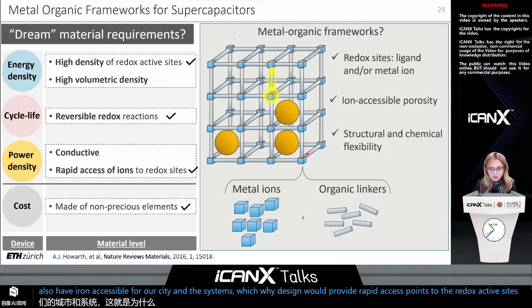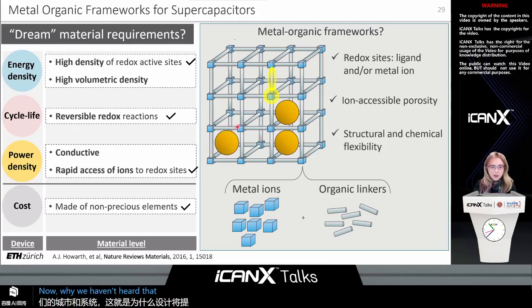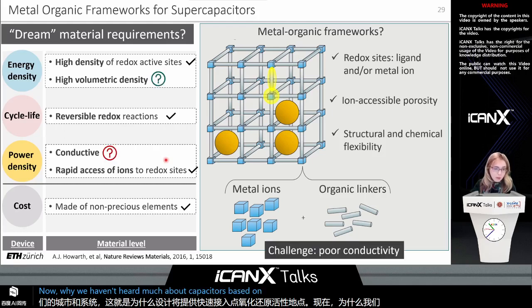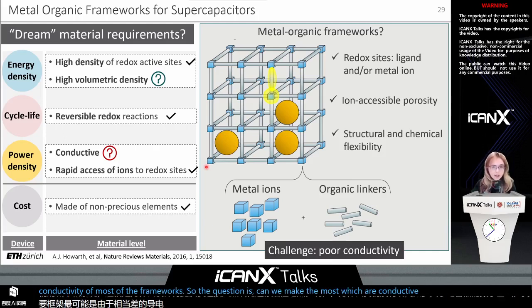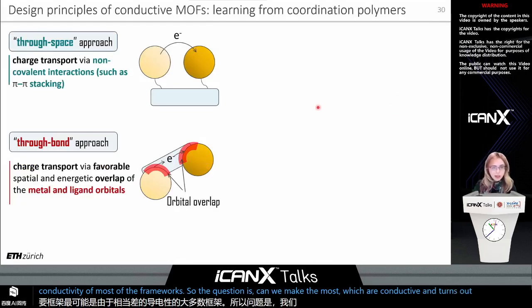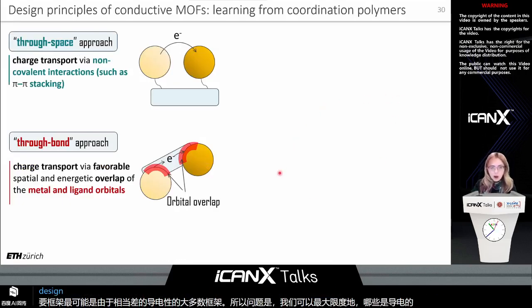Now, why haven't we heard that much about supercapacitors based on metal organic frameworks? Most probably due to the pretty poor electrical conductivity of most of the frameworks. So the question is, can we make MOFs which are conductive? And it turns out, if we adopt the design principles of conducting coordination polymers for conducting MOFs, this can be achieved.